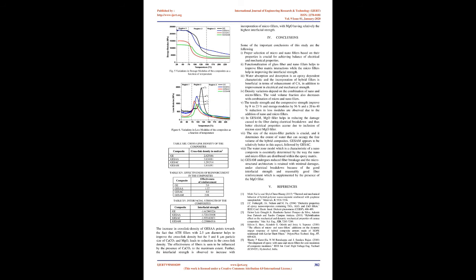Impact of fillers on physico-mechanical properties. Role of hybrid filler on density and microstructure. The role of fillers on the density of the composites can be understood from the results of composites shown in Table 11. The differences in density due to incorporation of a mono-nanofiller, combination of 2 nanofillers and combination of 2 nano and 1 microfiller is evident from the results of the table.